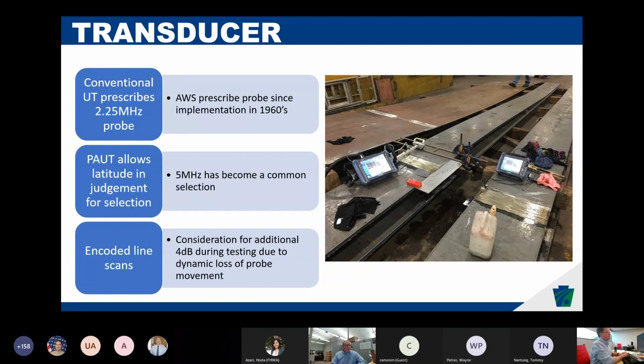But phased array allows a little bit more latitude in judgment, and it's been somewhat commonly accepted throughout the different industries that a 5 megahertz probe is the one that people just fall back to. 5 megahertz with 64 elements or 32 elements, being used to get basically the same type of, if not better, scanning. And then we're no longer doing a raster type scan. We're doing encoded line scans where instead of moving forward and backwards across the full length of the joint, we would just move parallel to the length of the joint, but the calibration process would be done manually.